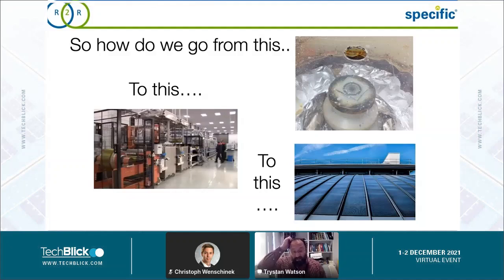The thing with spin coating is it's really good. It's a dynamic process — it evaporates the solvent and nucleates and crystallizes the perovskite all within a really short timeframe. It lends itself to the use of anti-solvents to really encourage that crystallization and nucleation. When we think about the upscaled version, where we take a liquid and dump it all onto the substrate at once, a lot of those dynamic processes are not possible. We have to almost invent the next set of technologies to get perovskite to crystallize in a homogeneous fashion, which is our ultimate challenge.